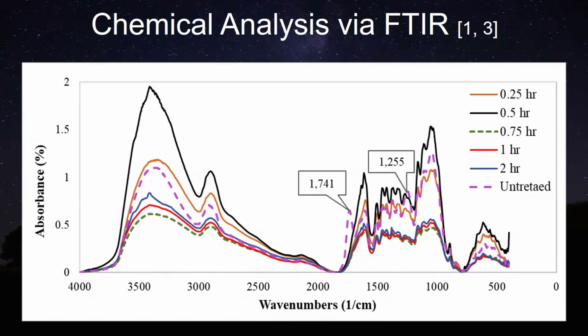And then we did the chemical analysis, which is a combination of untreated and treated fiber altogether. And you can see that I precisely marked 2 points, those are 1741 and 1255 wave numbers. So those peaks are actually representing the presence of hemicellulose, and you can see that is in the untreated. However, when we did the treatment, this has been replaced. With the treatment, we were significantly able to reduce the prevalence of hemicellulose, because hemicellulose is too hydrophilic. So because of that, it absorbed water or moisture, and it deteriorated our thermal and mechanical properties.